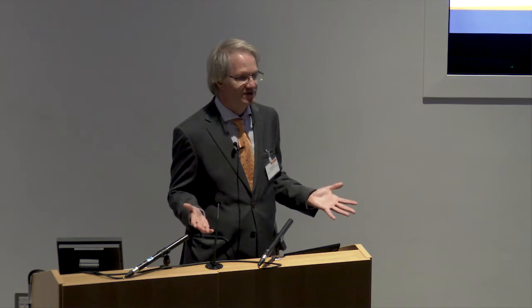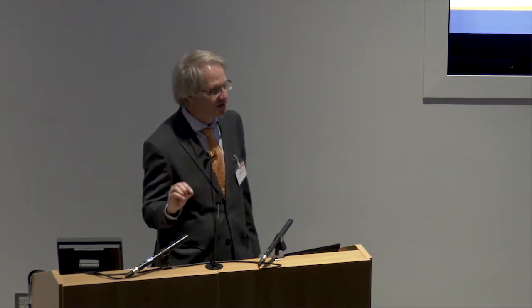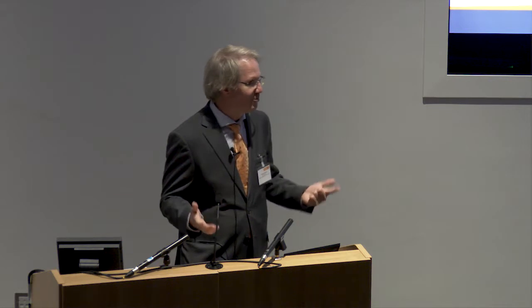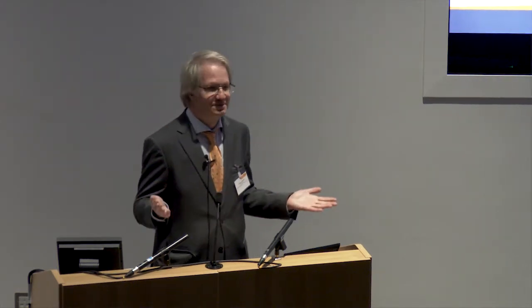But this group here, led by the ILT, investigated a process called laser polishing, which uses the laser itself as a polishing instrument. And the idea is to remelt a small layer of the part and to use the surface tension to reduce the overall roughness of the part. And the requirement is no additional materials should be used, it should run automatically, and of course the process should not destroy or weaken the overall mechanical properties of the part. A nice shiny part with weak mechanical properties is not worth anything, and so this is an interesting topic of the work done here.